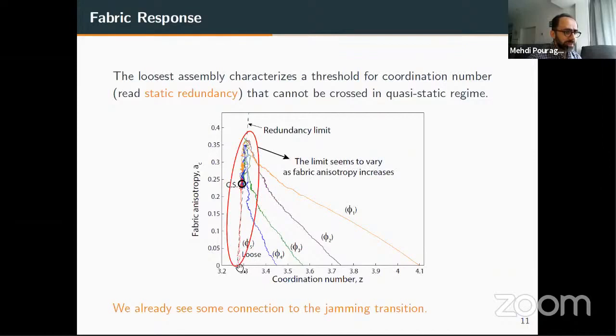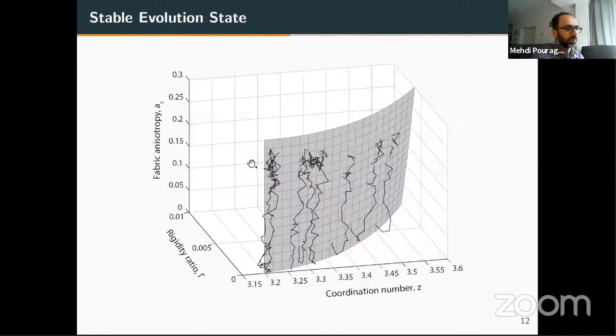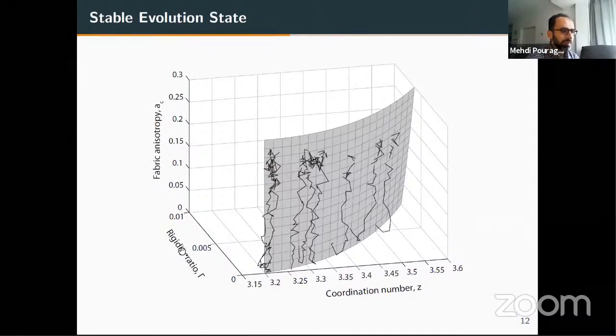Okay, so we see the threshold, and the threshold, as we see here, is defined. If you go to the loosest possible sample, it gives us that line. It gives us a threshold. So next step, we simulated a bunch of different loose samples to get this limit. So we changed the confining pressure, or the lateral pressure, or hydrostatic pressure, and we get a sort of manifold in the space of coordination number and fabric anisotropy, and also rigidity ratio. This rigidity ratio is basically the relative displacement at contact points with respect to particle size, which is related to hydrostatic pressure divided by the stiffness of particles. So it's a comparison between applied stress and the stiffness of material, and we can see that we get a manifold by connecting all those loose simulations.